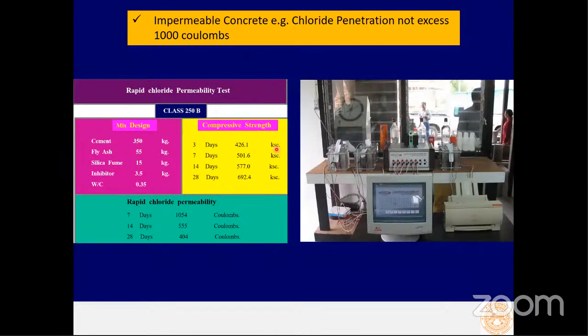Not only the protective system of cathodic protection, we also designed the mix design of a special concrete type. At that time, we used fly ash and silica fume. The fly ash helps the concrete with the permeability condition. So we try to control chloride penetration to not exceed 1,000 coulombs, so that we ensure no corrosion problem in that pier. And if you see the mix design and the compressive strength results from 3 days to 28 days, you can see that at 3 days, the strength of the concrete pier comes to about 426 kilograms per square centimeter, or about 40 MPa, okay?